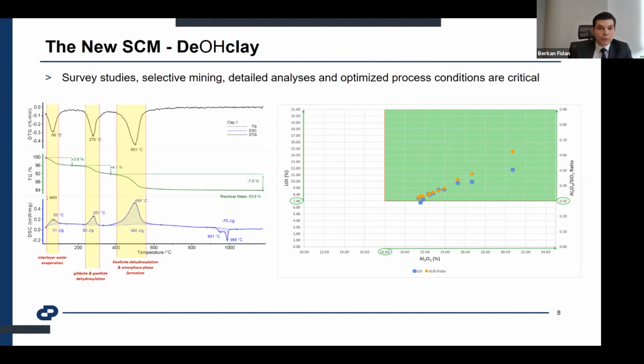This is just an example: as you can see, when we heated up the material, up to 100 degrees some interlayer water evaporated, and then there's an endothermic reaction, related to the gibbsite and goethite contents in our composition, and some clay minerals could also include it. After that, another peak starts just after 400 degrees, and that's the kaolinite, showing the amount of kaolinite. Then heating continued. When we reached over 950 degrees, the exothermic reactions started. That means crystallization, and new phases start to appear, like cristobalite, mullite, and other spinels. That means we're starting to lose its reactivity.